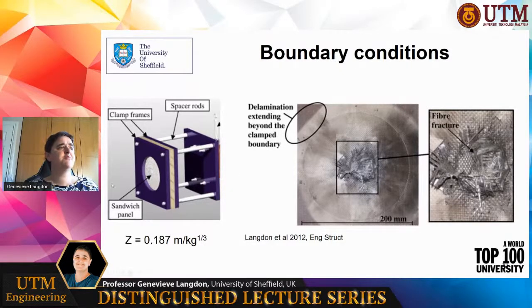So you detonate some explosives near the front of the panel. The panel transfers that momentum through the pendulum. The pendulum will then give you an impulse reading because you can measure the swing of it. And the panel itself gets damaged by the explosion, and you're able to then do very careful post-test analysis of those panels. And here's an example.